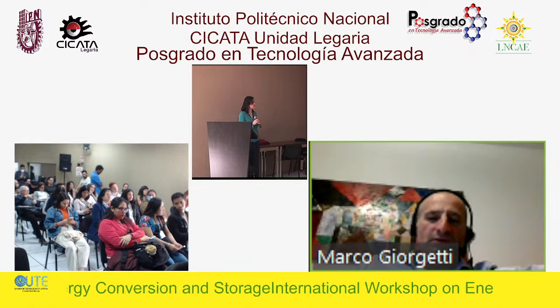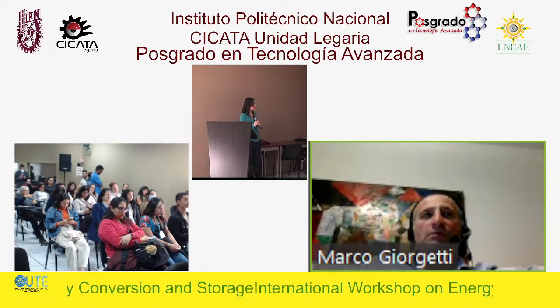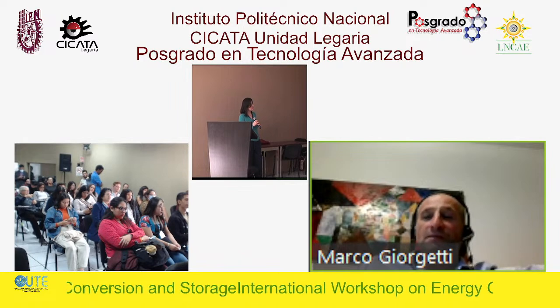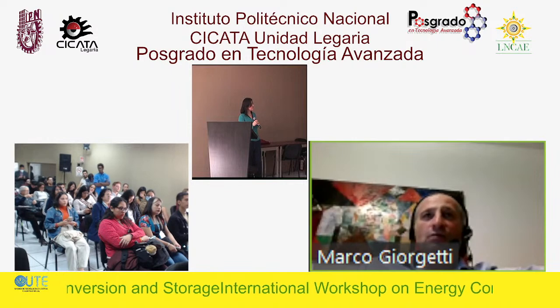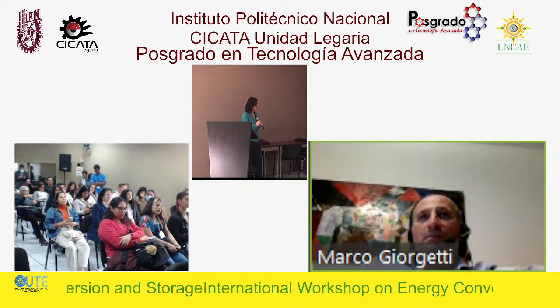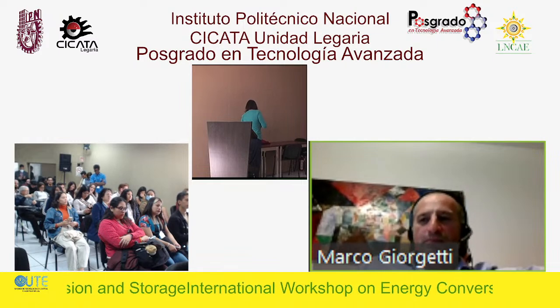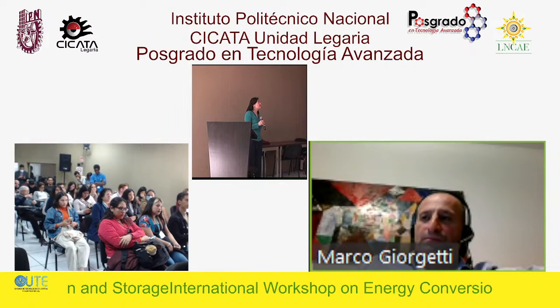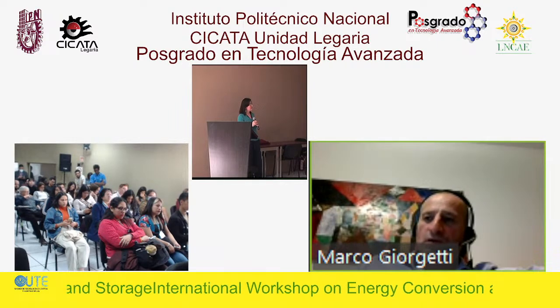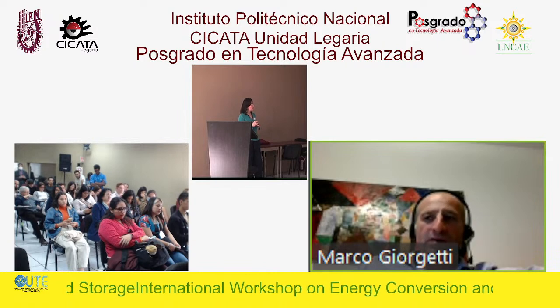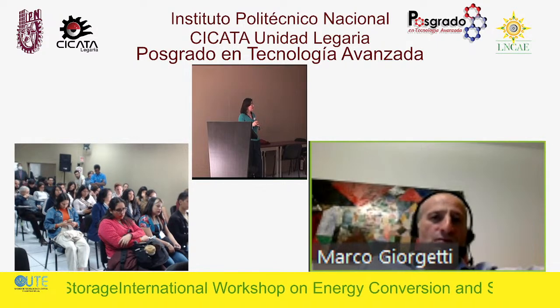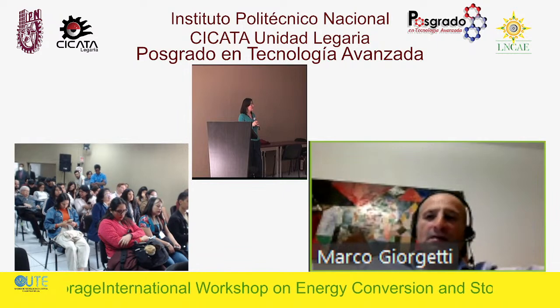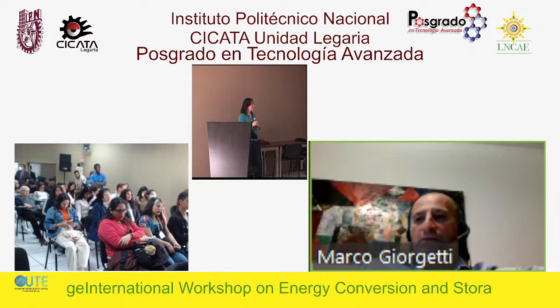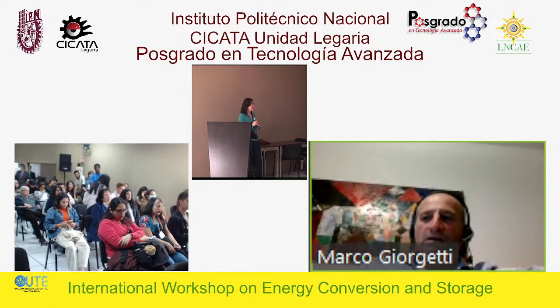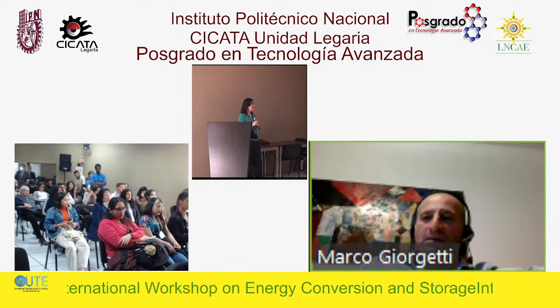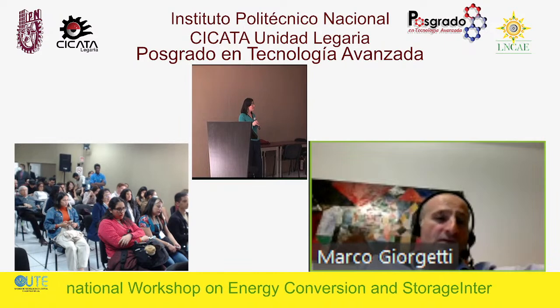Vanadium, what would be the benefit of using vanadium? Vanadium is probably at 1.3, 1.5 volts with respect to lithium. This means that if you combine this vanadium anode with something that works at 4 volts, you end up with a battery of just 2.5 volts. That is probably not good. So I think one of the most interesting things of the application of PBA in batteries is really the cyclability, and probably the solution is just stationary application, for stationary batteries, okay? So batteries, even though the volumetric energy density is not high, for load leveling in stationary applications. I see probably the future just in that application now.